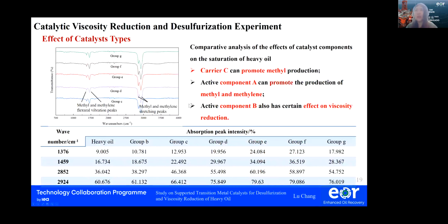Then the role of carrier C and active components A and B in the viscosity reduction process was analyzed. The FTIR results show that carrier C in group C can promote methyl production due to its strong surface acidity and better pore structure. Active component A can promote the production of methyl and methylene. Component B also has some effect on viscosity reduction, but it is not the main factor. However, from the previous slide, the main function of component B is to reduce the asphaltene content because it can inhibit the production of coke.